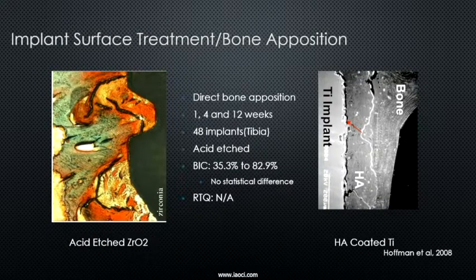So when you have integration of implants, for example, you have a zirconium oxide or a zirconia implant compared to an HA-coated titanium implant, you have an interface between the implant and the bone. That's why sometimes you see implants fail and come out. The HA stays in the bone. The metal implant comes out because the bone was integrated to the HA, but the HA got separated from the implant over time. That happens. Whereas with zirconia, you have a direct integration of the bone into the implant itself.